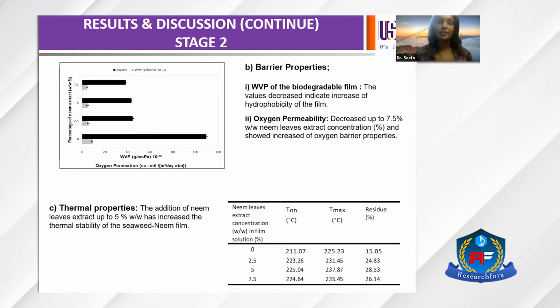The next one is the barrier properties. I did two different barrier property tests: one is water vapor permeability, the other is oxygen permeability. The water vapor permeability decreased because of increased hydrophobicity. As I told you, there is hydrogen bonding between seaweed and neem, so the hydrophilicity of the film reduces. When hydrophilicity reduces, water vapor transfer reduces and water vapor permeability reduces. So this shows a very good water barrier property. Oxygen permeability also decreased as the concentration increased up to 7.5% of neem leaves. This is because the addition of neem leaves can increase the film thickness, and there is hydrogen bonding, which can decrease the oxygen permeability. That is why the oxygen barrier, which is very important, increased. So this is for the barrier properties.